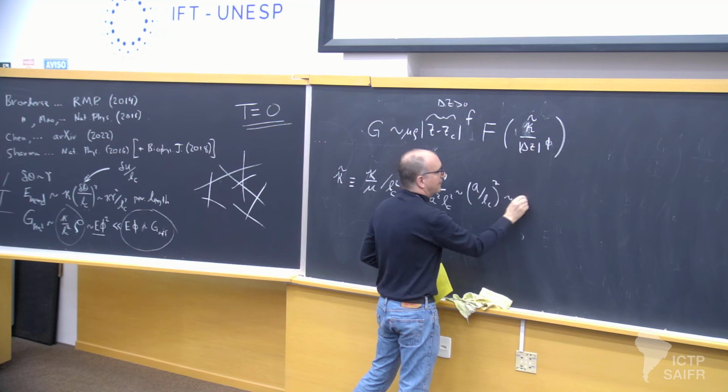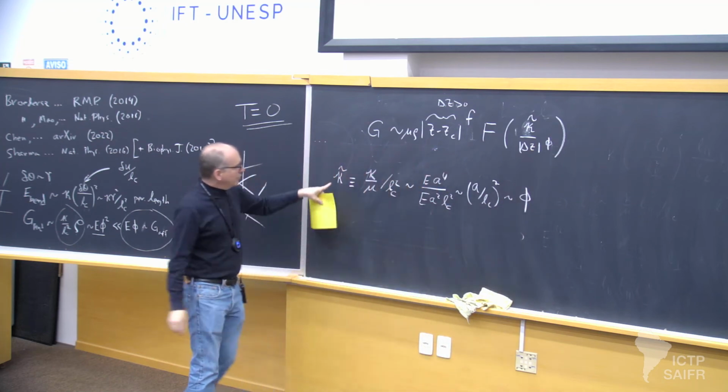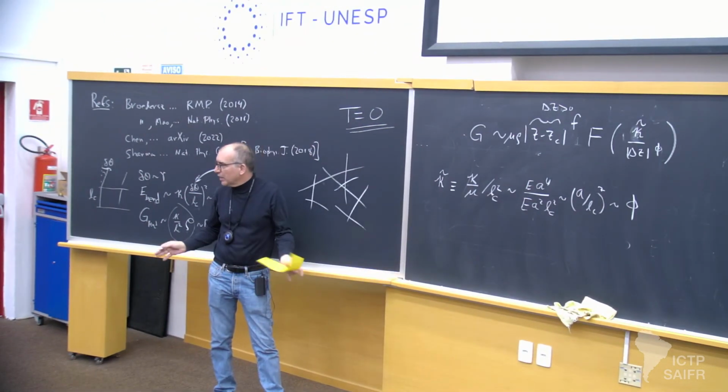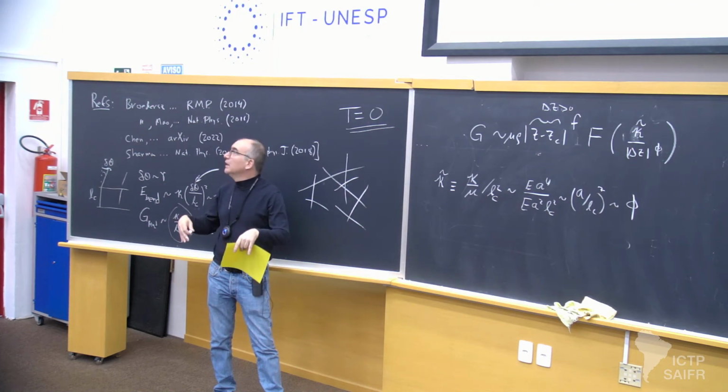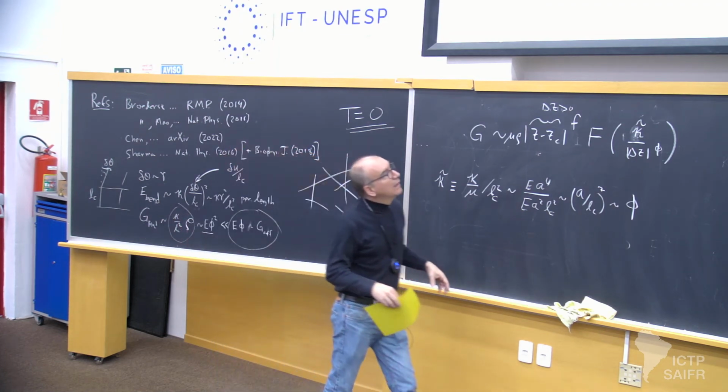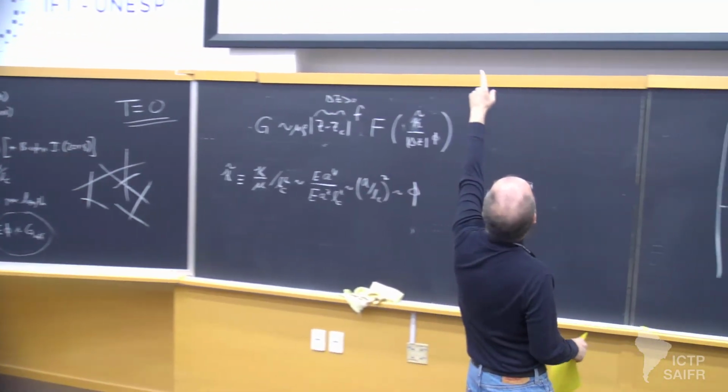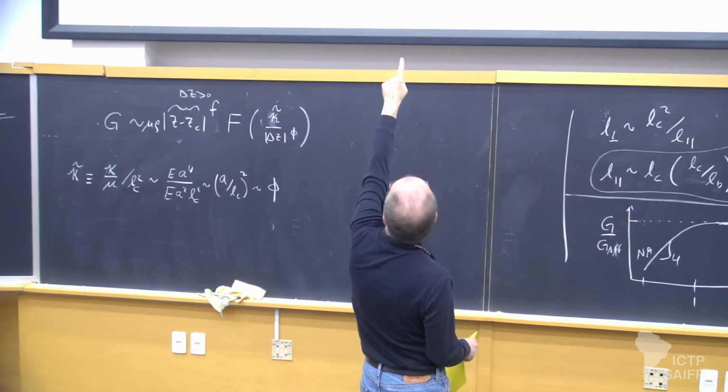Okay? So the natural dimensionless measure of bending rigidity is just the volume fraction. And at volume fractions of order 10 to the minus 3, a tenth of a percent, it'll correspond to one of those curves there, I guess the light blue one.